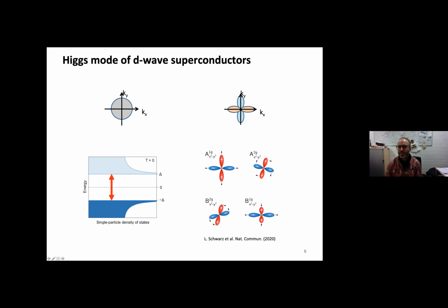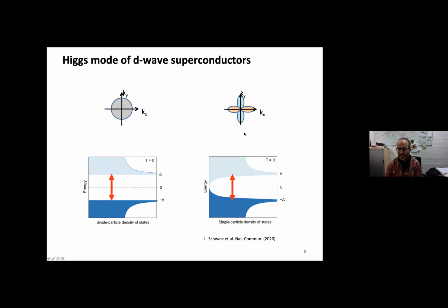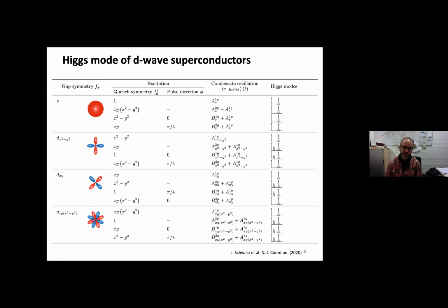However, in these D-wave systems, we see already momentum dependence. We have a change of the superconducting gap from 0 up to delta max in the system. So that means inside the gap, depending on momentum, at every energy, we will find some hot quasi-particles in the system, and that will lead already to a strong damping of superconducting Higgs oscillations in the system after a quench.